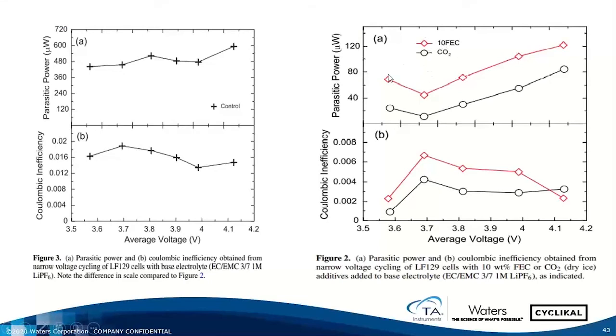Notice what happens to the thermal power when we're using 10% fluoroethylene carbonate in our EC-EMC blend. The parasitic thermal power is just dramatically lower, and it's even lower still for the carbon dioxide additive to the electrolyte. So again, very supportive of the effect of cycle life on the parasitics that we're evolving from just the electrolyte and its impact on silicon materials.